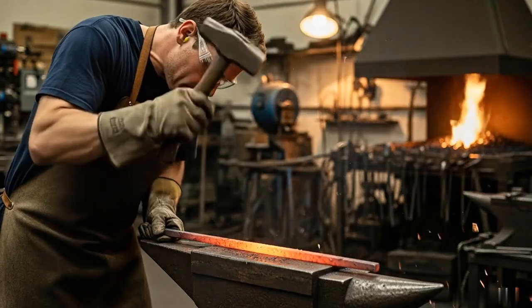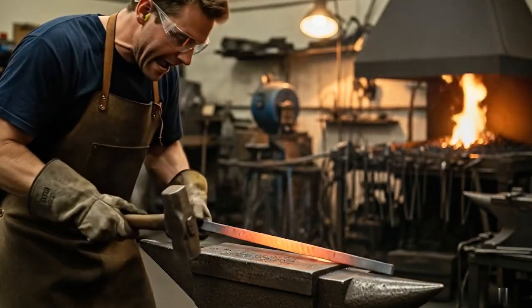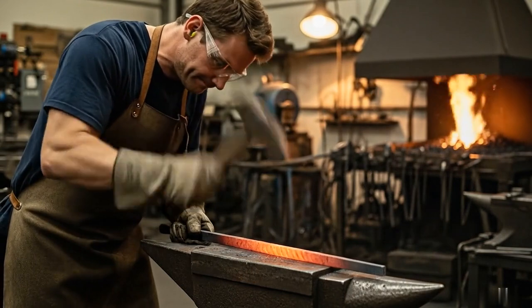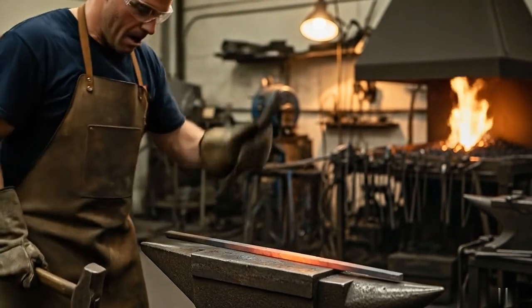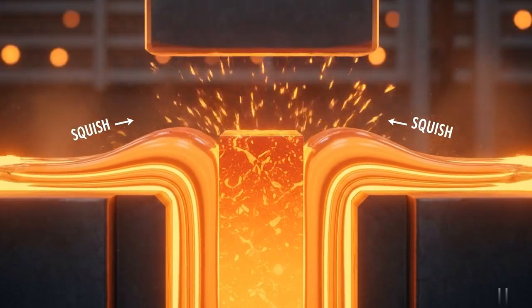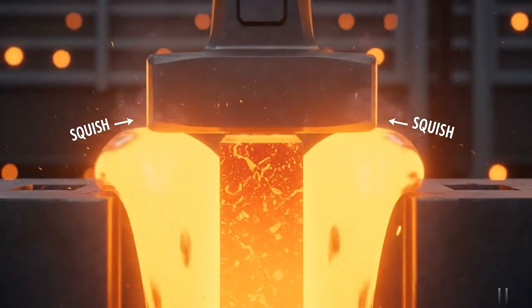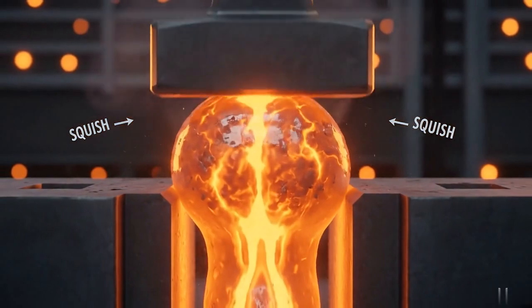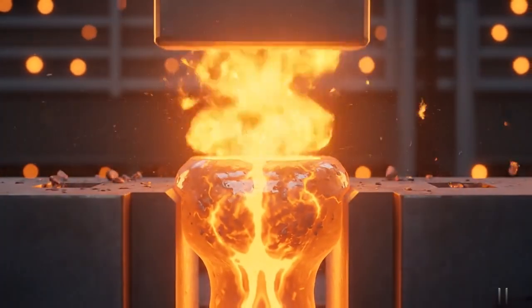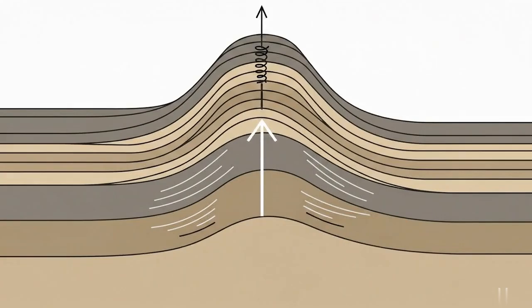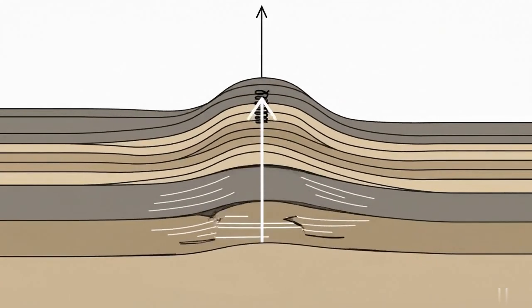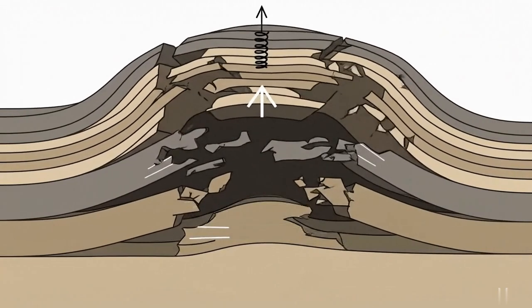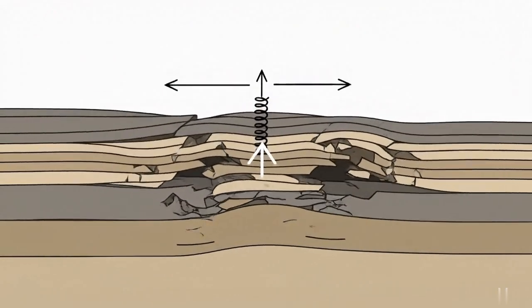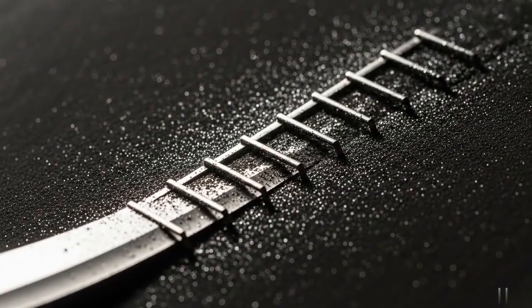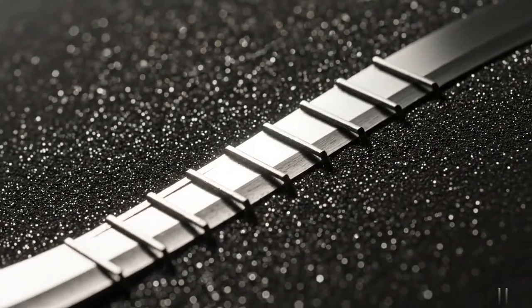I heat it up, bring it to the anvil, and now I hammer the blade flat again. As the hammer falls, the metal on the sides of the grooves gets pushed down and inward. As it does that, the layers underneath are forced to bulge upwards, disrupting the straight lines. When I grind the blade, I will cut across these waves, revealing a pattern like ladder rungs.